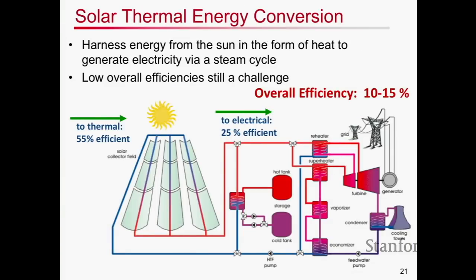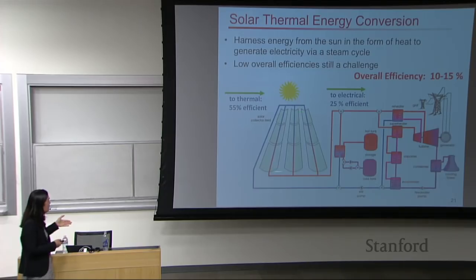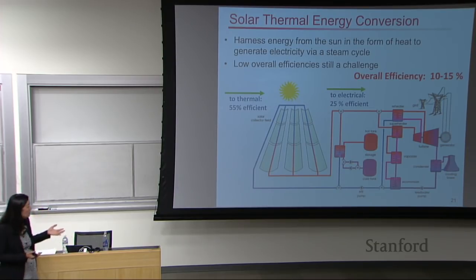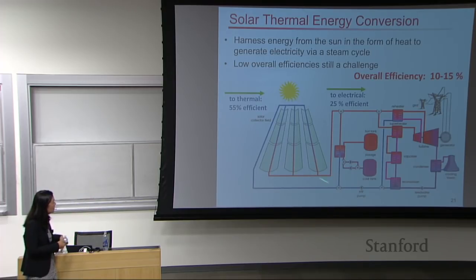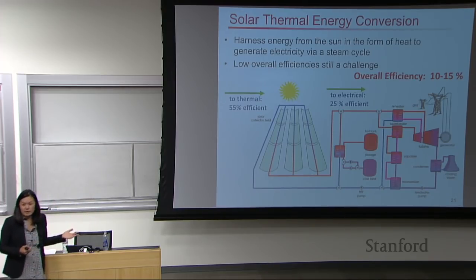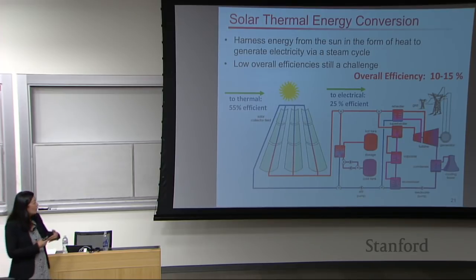When we look at the internal workings of a solar thermal power plant, certainly when we think about the overall efficiencies, they're still pretty low. They're on the order of about 10 to 15%. And the reason for that is there are multiple conversion processes along the way, from the sunlight to thermal via these collector fields. For example, what's shown here is a parabolic trough configuration. The solar to thermal conversion process is only about 55% efficient. And then from the thermal to electrical, using this steam cycle here, it's about 25% efficient. So collectively, that amounts to this 10 to 15% overall conversion efficiency.